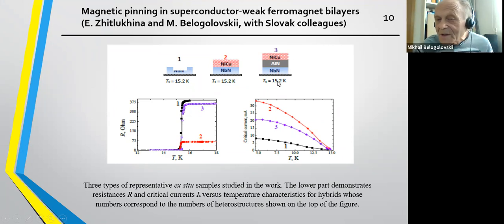So such a three-layer system, where we had a superconducting film and a weak ferromagnetic film, which were divided by ultra-thin aluminum nitride, so by an insulator. And in this case, the critical current density was strongly increased, while the critical temperature remained the same. So our explanation is that here there is an interaction between the magnetic field of the vortex and the magnetic texture of the weak ferromagnetic layer.